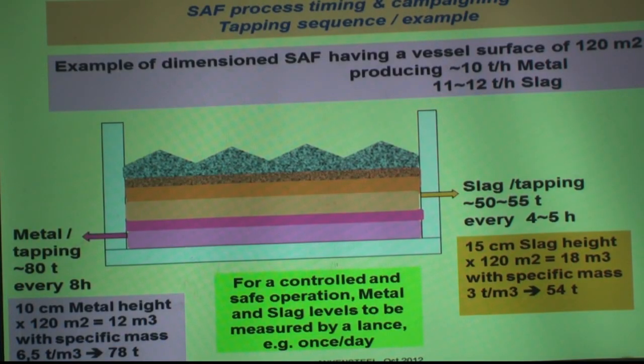And in the case of another furnace, I was there in the United States. There, same problem, but they had this type of cooling. And actually, when you have this, the slag normally, this is done to have the slag like this, and here you have solid. So this is not aggressive. Even if the slag goes a bit higher, it's normally not a problem. But if you don't control the height and you have slag until here, that was the case,